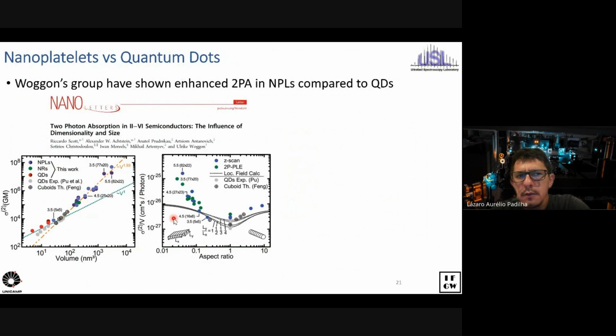And other groups out there have thought about ways. One way, for example, would be to play with the shape. For example, the group of Woggon in Germany has proposed that you can get larger volume normalized two-photon absorption cross-section by simply using, for example, nanoplatelets or nanorods. And their argument is that you change how the local field penetrates the nanomaterial, and then you manage to enhance the effective response. When you have more field, you're going to have more nonlinear optical response.